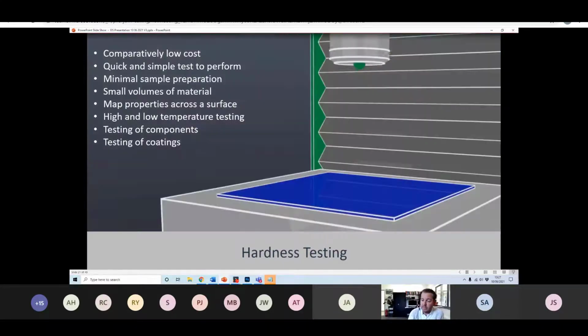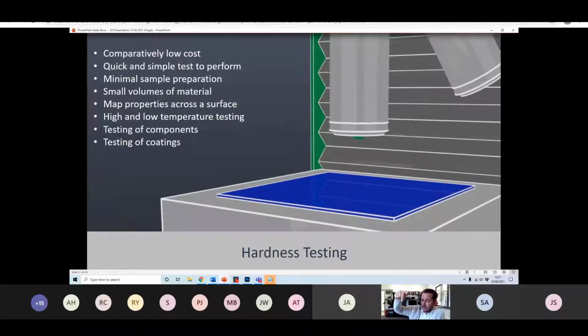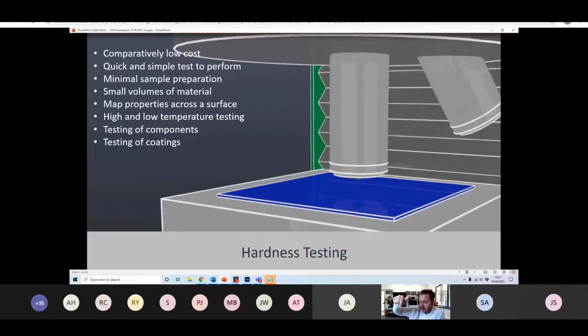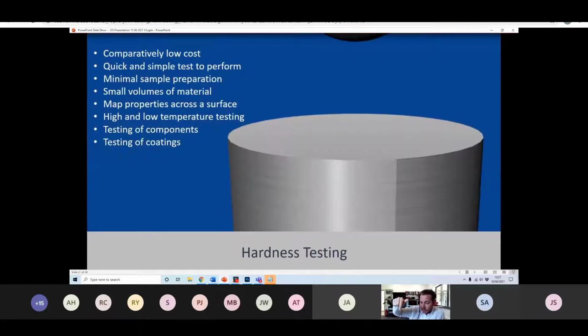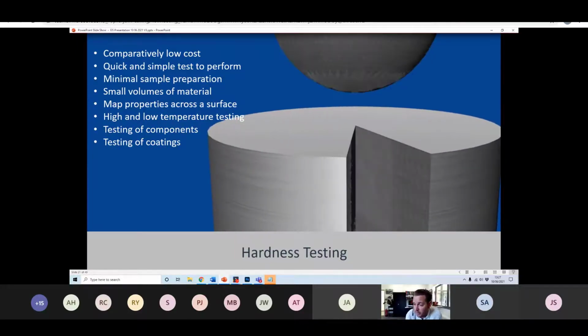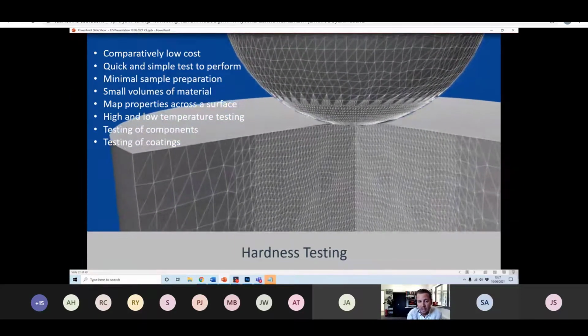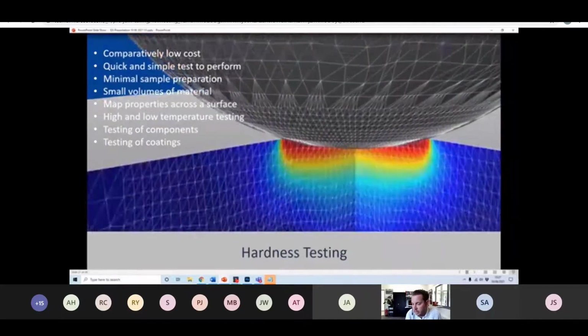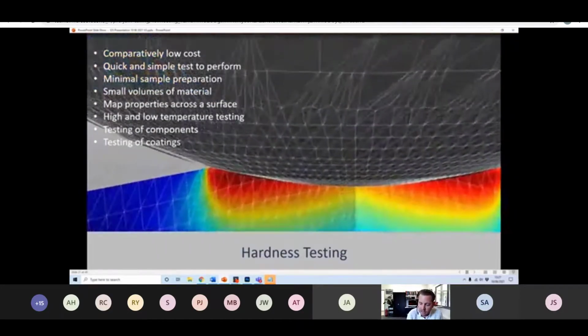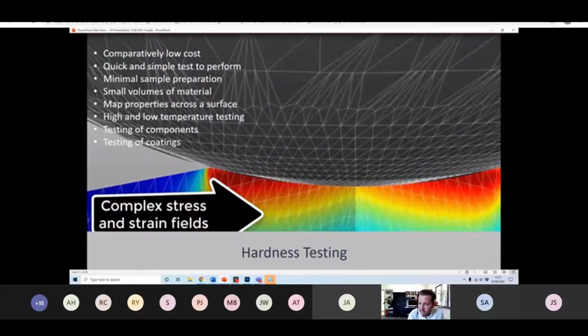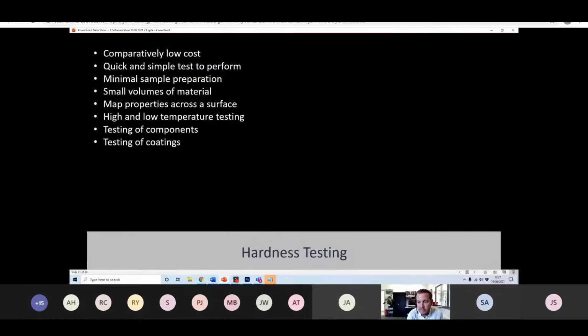And the process is very simple insofar as you simply take a very hard sphere or a pyramidal type shape or a conical type shape, and you push it into a material that's a little bit softer. And you can measure things like the diameter of the spherical indent or the diagonal across a pyramidal indent or something like that. You can measure a hardness number, and that's all very simple and very easy and reasonably intuitive as well.